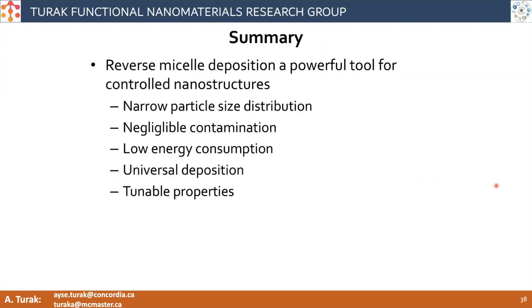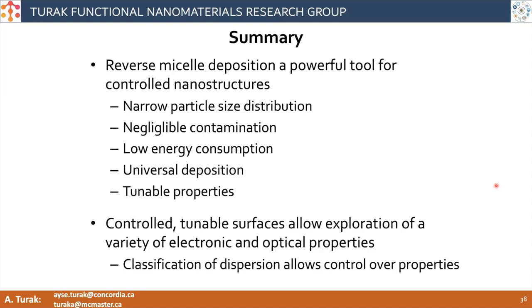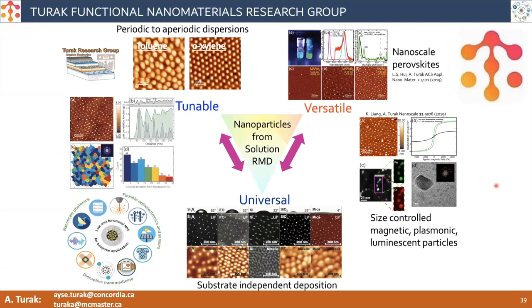So I hope I've been able to convince you that reverse micelle deposition is a powerful tool to achieve a wide variety of nanostructures that have very small size distributions that are basically contamination-free. I didn't talk about the purity of those phases, but we can get very nice crystalline structures without requiring a lot of energy. Because of the solution nature of it, we can deposit it almost universally on almost every surface, and we still have room to tweak the properties, right? We're not locked into a particular material system. We're not locked into a particular size. And so having these controlled tunable surfaces where we have an array that we can understand now gives us access to things that are really hard to decipher, such as the role of geometry in developing, for example, the electric field through an organic device, things like this. So this is my overall pitch of everything.